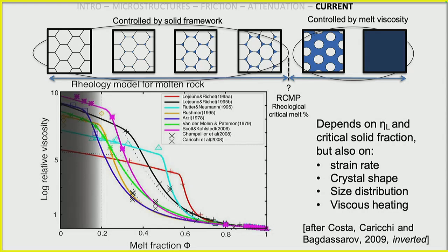But in fact, we don't have a curve that describes all this. Folks looking at rock, at molten rock, have this compilation of numerous studies, and they've described that basically you have this decrease with melt fraction that starts here, and then there's a kind of precipitous drop in viscosity, which happens at this critical melt fraction. So what is that? That's just basically when it stops being all solid, and now the solids aren't controlling the framework, but the melt is.